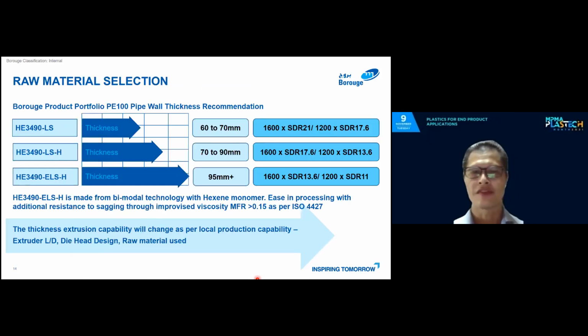Here is just a schematic of grades recommendation for the sizes that are required. If we need a 60 to 70 mm wall thickness of the pipe, our standard PE100 HE3490-LS would be suitable. If you have anything that's more than 70 to 90, then I would recommend LSH material to be used. Of course, if you have anything that's more than 95 mm, the best in class would be ELS-H.